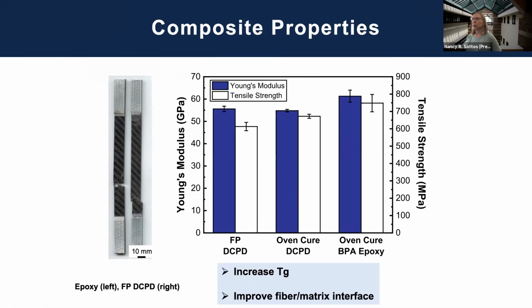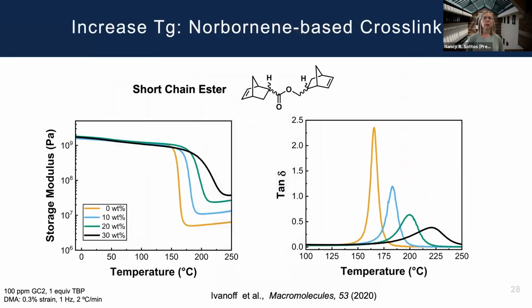And there's been 2 things that we have been focused on and working on to improve properties. One is to increase the TG of our composites, get the glass transition temperature, basically get the cross-linking up, and also to improve the fiber matrix interface. These Toray fibers that we've been working with are largely optimized for epoxy systems, and we have been working on different fiber surface treatments to improve adhesion with dicyclopentadiene. And I'll just quickly touch on recent work in these areas.